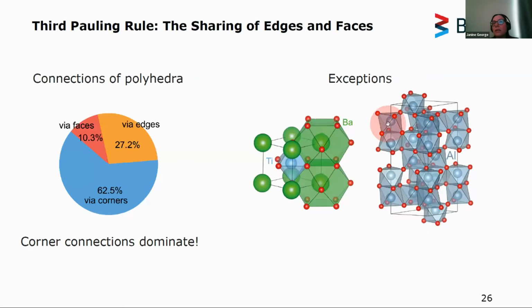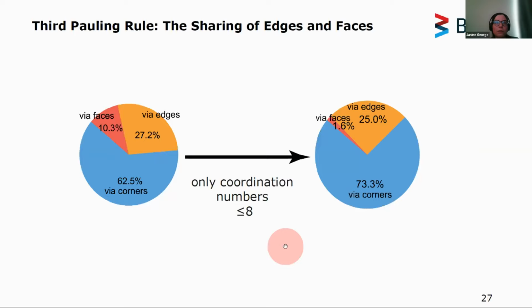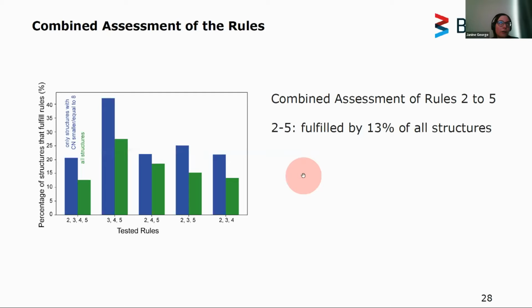corundum structure type. We were able to improve this rule by only focusing on coordination numbers smaller than 8. And then you can see that the face connections really vanish. And then you have a better agreement with what Pauling has seen. So we found a lot of exceptions also to the other rules.